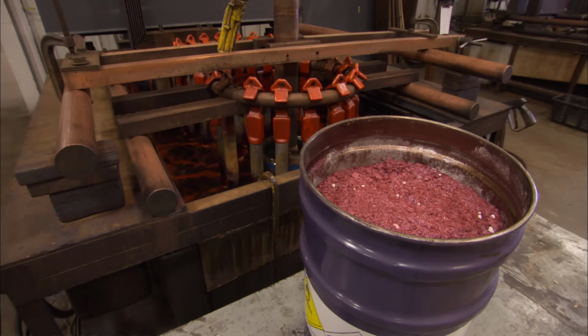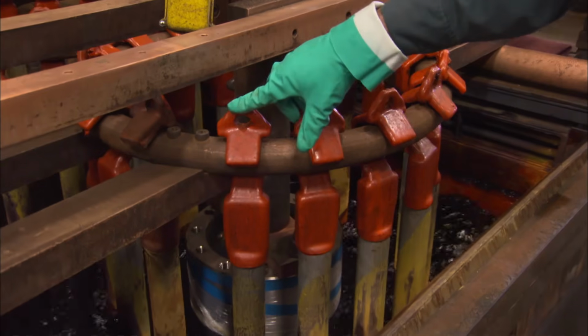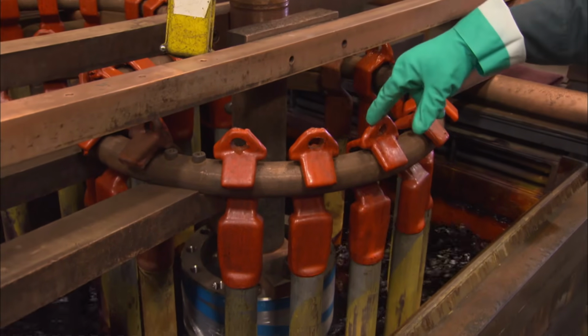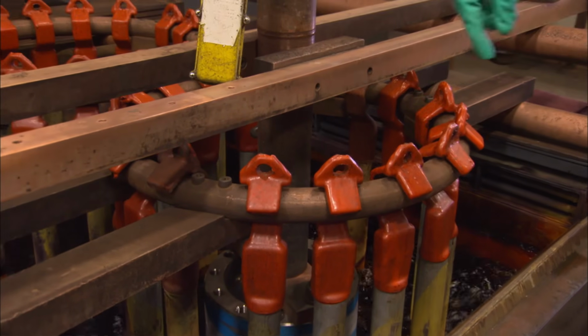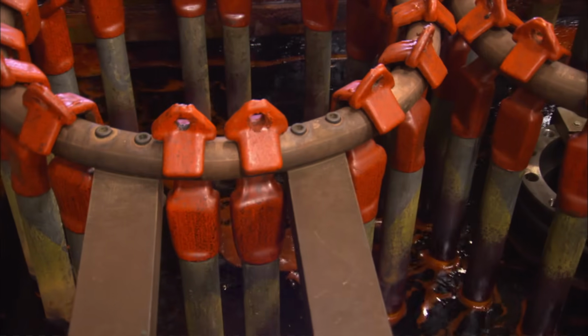A metal bar connected to the piston gives it a negative charge. Lead rods surrounding the piston carry a positive charge to the chromium particles in the bath. Sulfuric acid breaks down the red flakes, pulling out the chromium ions. Those ions move through the solution and then attach to the piston, leaving a shiny, metallic surface.